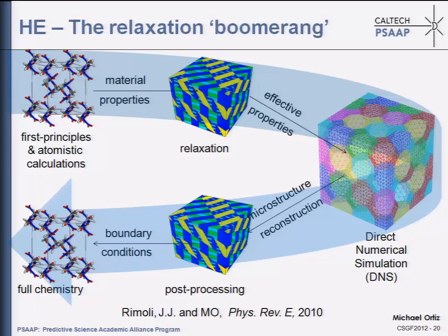So then this effective behavior is what we use here at the macro scale. We do some simulations. I'll show you actual tests that are done in engineering labs. So in this way, you can bridge all the scales from atomistic to engineering testing. And then, because we're interested in hotspots, we look at individual material points, we query the microstructure, we look at the extremes of the distribution in terms of pressure, deformation, temperature, and then we pass that back to our quantum chemistry colleagues, and they use these histories as initial conditions for carrying out full chemistry simulations at individual hotspots, and determine whether at that particular hotspot, in effect, there was initiation or not.